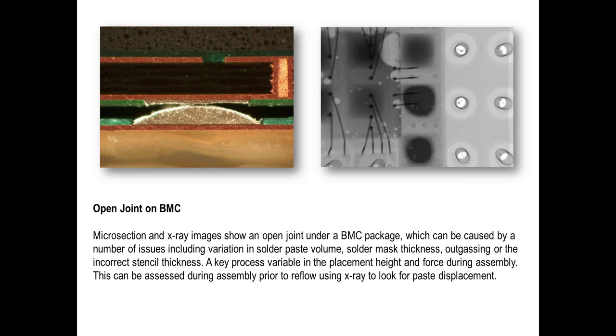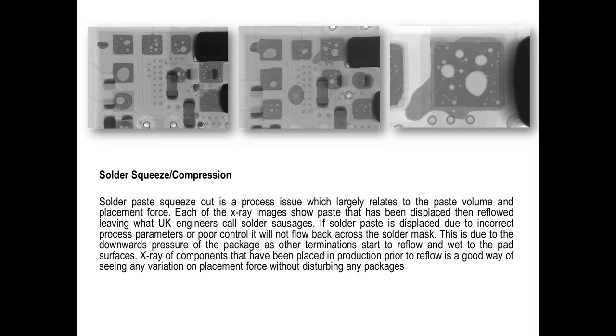During the reflow process, volatile materials tend to climb within the solder joint and come up to the pad surface. If a solder joint hasn't formed at that point in time and there are volatile materials against the surface where the solder is, it's just a gaseous layer which is preventing good soldering and good wettability, which could lead to an open solder joint. And it's something that certainly people processing these parts have experienced over the last few years.